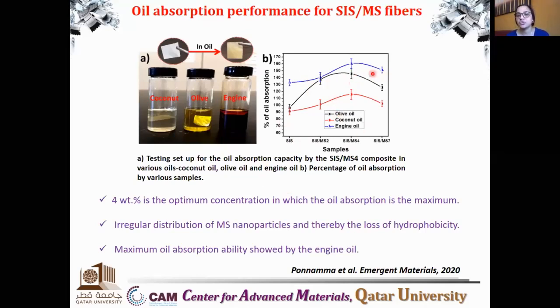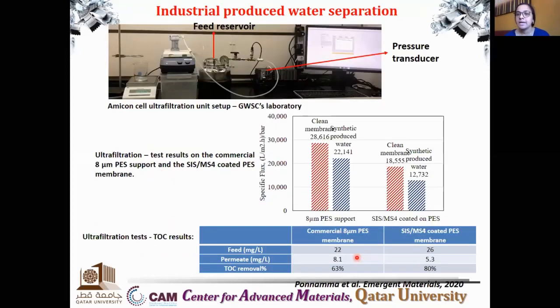Here also the engine oil showed the highest performance, maybe due to the viscosity and density effects. The irregular distribution of mesoporous nanoparticles leads to the loss of hydrophobicity. Maximum oil absorption was shown by the engine oil. This is another highlight of this research. I told you, because of the mesoporous silica, we cannot completely expect the material to be super hydrophobic. We can expect the hydrophobicity, but not that much when compared to the polystyrene or carbon nanotube composite.